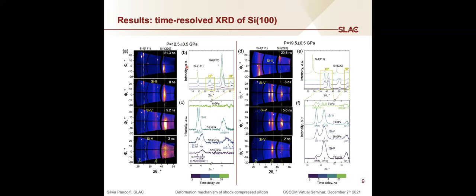So I'm going to start with this lowest pressure time series at 12.5 gigapascal. In this case, we have seen the appearance of the signal of high pressure phases. However, the signal is pretty noisy and quite low, so a precise deconvolution of the phases was not possible. We think, because of the densities and because of the pressure, that it is a mixture of the silicon II and silicon 5 phase.